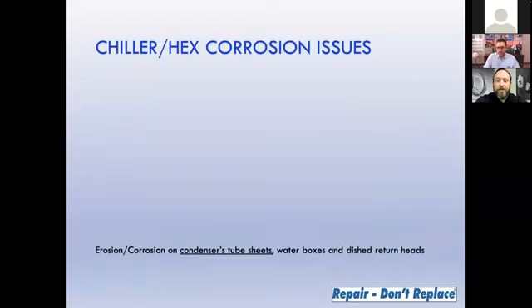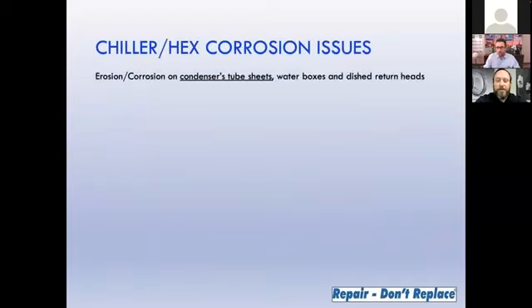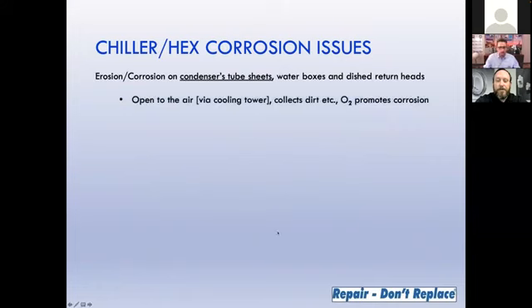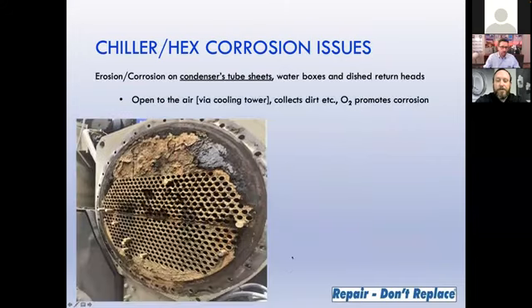The condenser of a chiller is usually where most of the corrosion issues present themselves. Being part of the open air system with the cooling tower, the unit collects a lot of dirt, mineral scale, debris, and a large amount of oxygen, which promotes the corrosion that we typically see when we come on sites for inspections. A large amount of mineral scale buildup on the tube sheet, corrosion underneath the mineral scale starting to form.